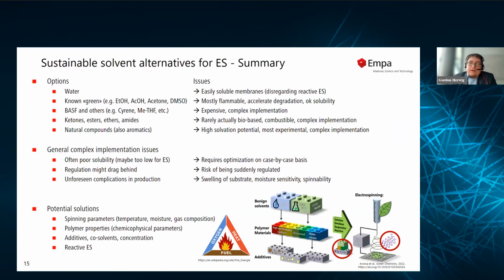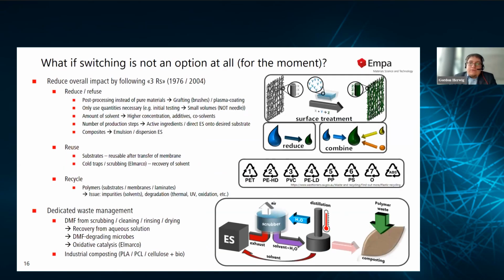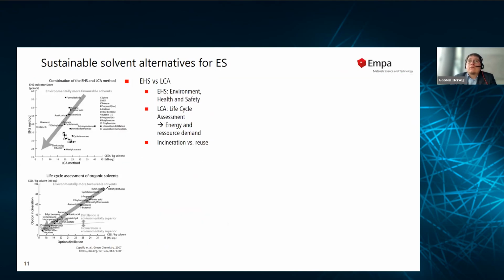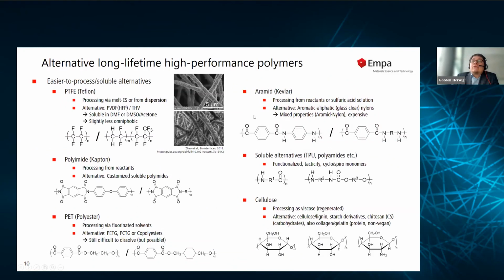Yes, so of course, always when you have higher temperature, there's a risk of oxidizing something. But in the case of the PTFE particles, they are very stable. So the idea is to choose a temperature where the polymer particle that you're using is still stable and starts melting, but not yet oxidizing. You're doing this whole thing under nitrogen atmosphere, ideally, so that it doesn't have a chance to oxidize in the first place. And that means it probably won't rip apart, as you mentioned.